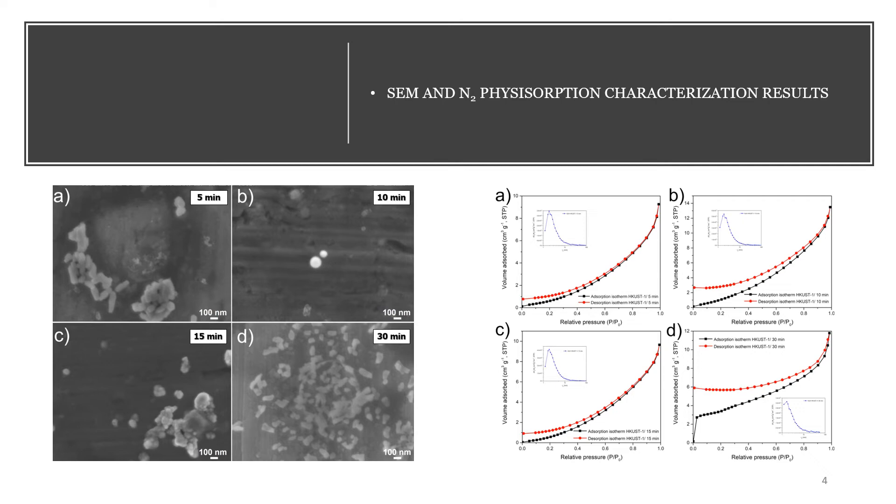Then, when the synthesis time reached 10 minutes, a redissolution was observed, and the particles exhibited a size of 83 plus or minus 29 nanometers with a quasispherical morphology.